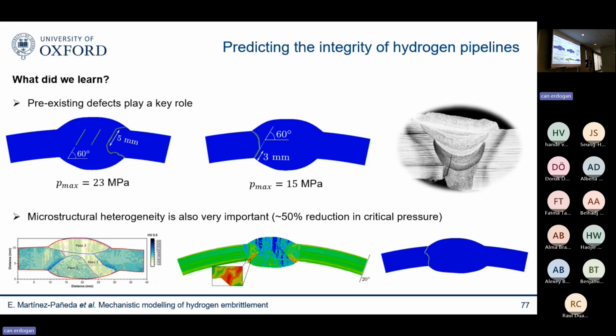And what I find quite interesting is that we published that paper last year, but a few months after we published the paper, they ran a full-scale experiment on a real pipe where they introduced a small notch, a 3 millimeter notch along the heat-affected zone in a weld, and they saw a failure pressure of 12 megapascals. So it seems that the model running months before under slightly different conditions was not too far away from the practical case.